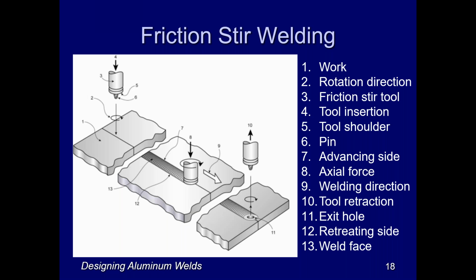You have in the upper left-hand corner here the tool, which is basically a rotating mechanism with a little pin. It almost looks a little like a drill bit. That's plunged down into the joint between two abutting aluminum base metal parts. It's rotated, and once the heat of friction gets up to a certain point, the rotating tool is traversed along the joint in the direction you see here, from the upper left to the lower right, and then finally withdrawn from the part.